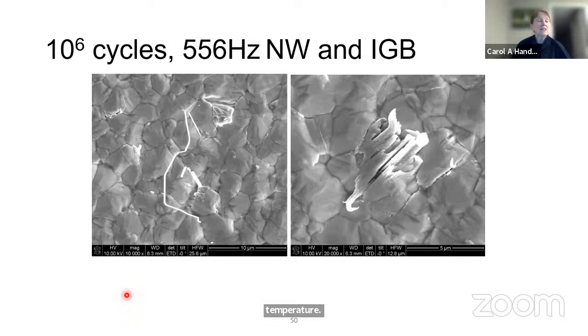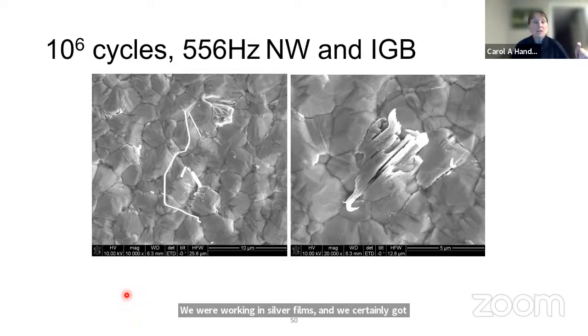I don't think anybody's tried in copper. We were working in silver films, and we certainly got hillocks to form in those films, which are short whiskers, where the height above the surface to diameter ratio is about 1:1. In gold, it's seen. I think it's the condition of having a film that's 60% or more of its melting point, a tenacious oxide layer, and there aren't many other stress relaxation mechanisms operating. It makes tin such a great whisker former. Cadmium also forms whiskers. Zinc is another system that forms whiskers prolifically.